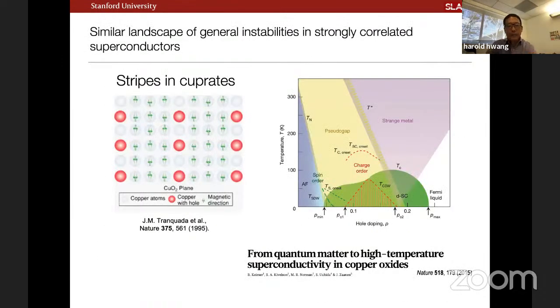So if we take a step back, we're building a picture of a rather similar landscape of instabilities to other strongly correlated superconductors, and of course, in particular, the cuprates. So the stripe phase, first seen by John Tranquada in the cuprate case. And as I'll try to spend a little bit of time on going forward, in this very complex phase diagram, we see this dome of superconductivity. We don't have this antiferromagnetic Mott insulator as a parent compound, but we clearly see that magnetic fluctuations are important and a fairly large energy scale in the system. And so these notions of competing or intertwined orders that are so prevalent in the cuprate discussion seem very relevant here as well.